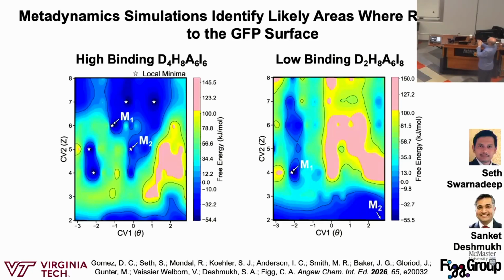If we compare that to a low binder, you see that maybe there's a minima here, there's a minima down here. This is a coil region, this isn't in the barrel region. But just by looking at these, you can see that the strong binders, depending on composition, show a lot more binding sites on the GFP surface than the low binders. We ran maybe 20 different sequences and compositions with this sort of computational analysis.